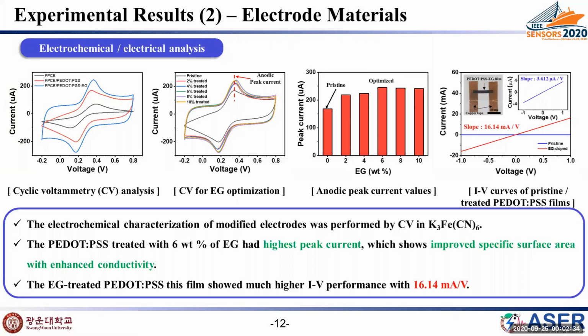For optimization, electrodes with PEDOT:PSS treated by different weight % of ethylene glycol were evaluated by CV. The highest performance was obtained at 6 weight % of ethylene glycol. Finally, to confirm the conductivity enhancement, we prepared a thin film for voltage sweep. As a result, we confirmed the conductivity was remarkably enhanced.